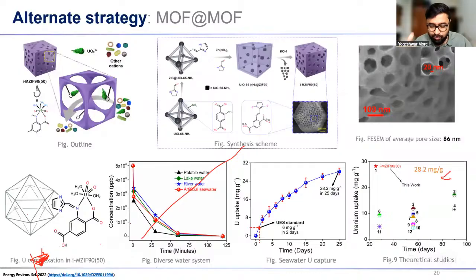So what we did, in whatever we did in the previous study, we tried to enhance its adsorption capacity in a different approach. We form a first crystal of UiO-66 MOF. What is UiO-66 MOF? The MOF is made up of benzene dicarboxylic acid and zirconium. Zirconium is very stable, SBUs, and we all know that zirconium is known for stable compounds. We form this zirconium MOF, and then this zirconium MOF has the amino functionalized linker like this.